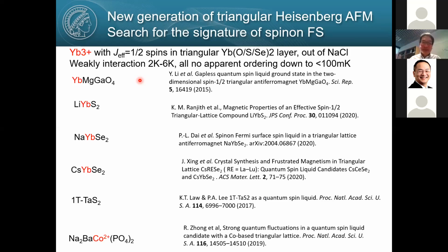So recently, instead of organics, inorganics, in particular those made of ytterbium, emerged in this kind of paradigm, and they are not organic, so they can do neutron measurements. And now people start seeing continuum excitation in triangular antiferromagnets. So here is a list of recently emerged triangular lattice magnets, and as you can see from the literature, it's quite recent. Many of them were published this year.